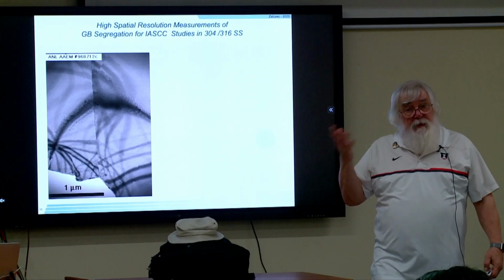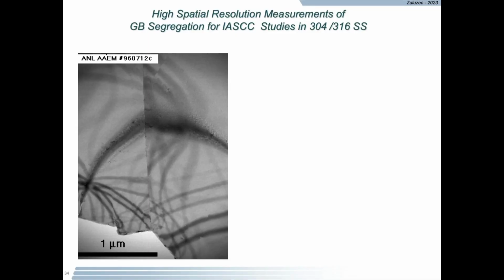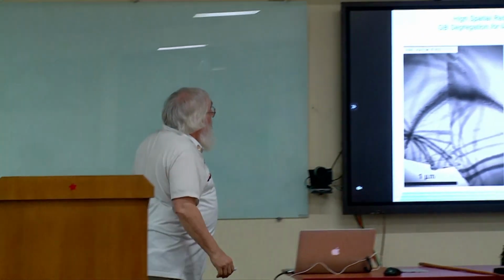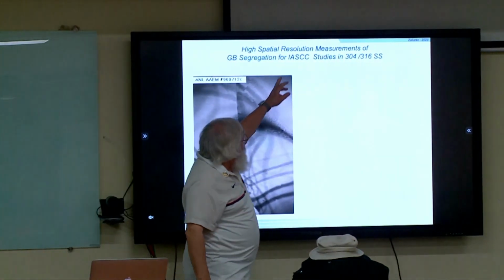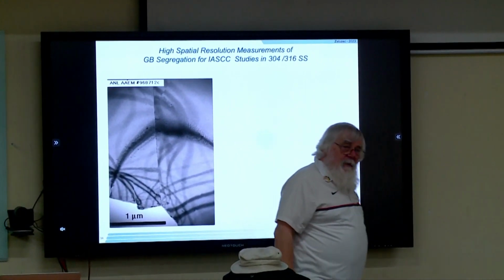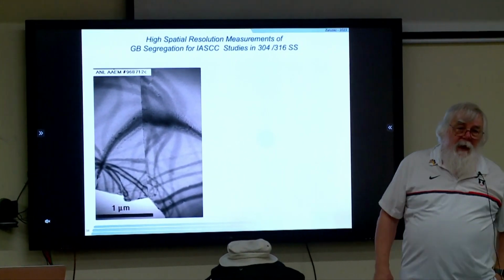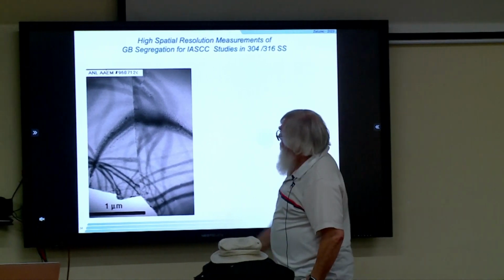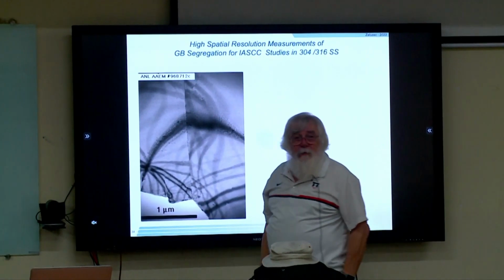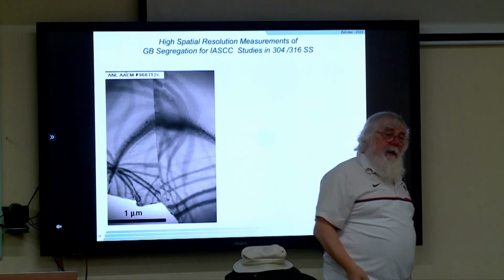What can we do with some of these analytical spectroscopies? Well, we can look at something like this, a grain boundary in a piece of steel. What's important about this particular grain boundary? It exists. But more importantly, this happened to be an intergranular stress corrosion cracking problem, and the cracking was happening right at the grain boundaries. And the question is why?